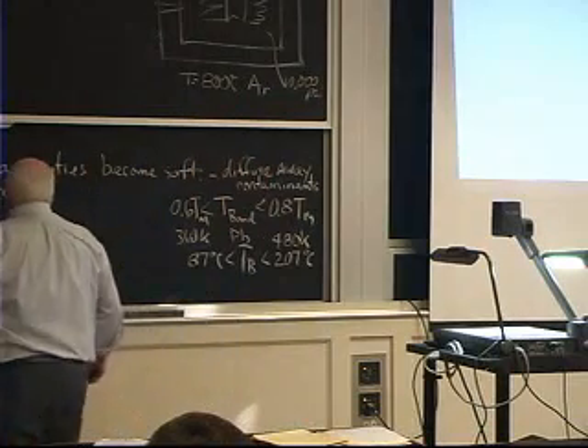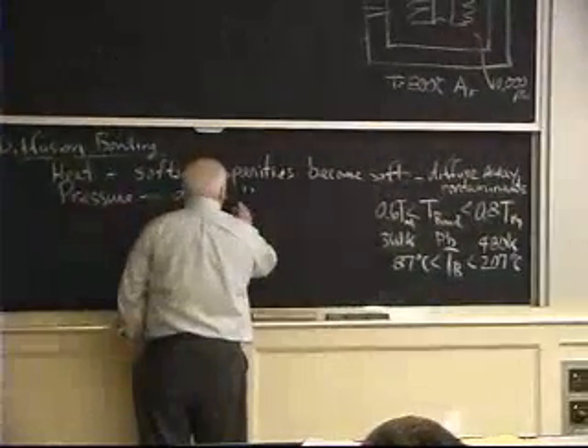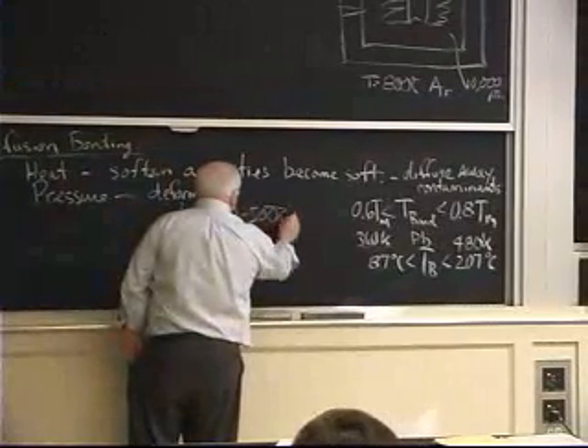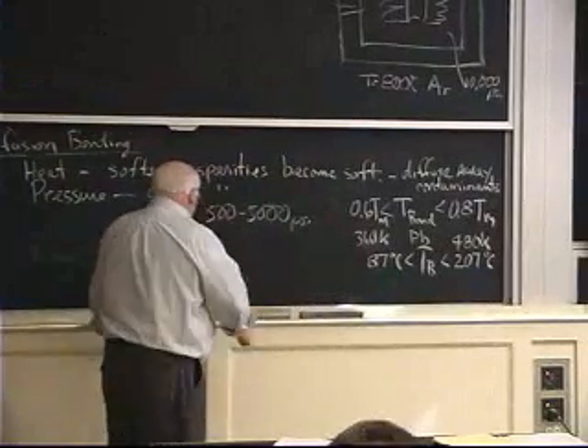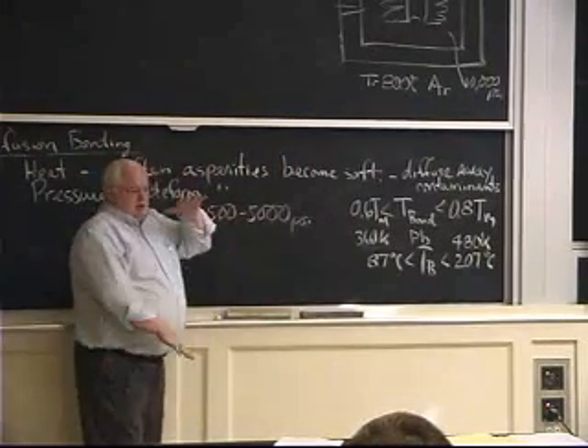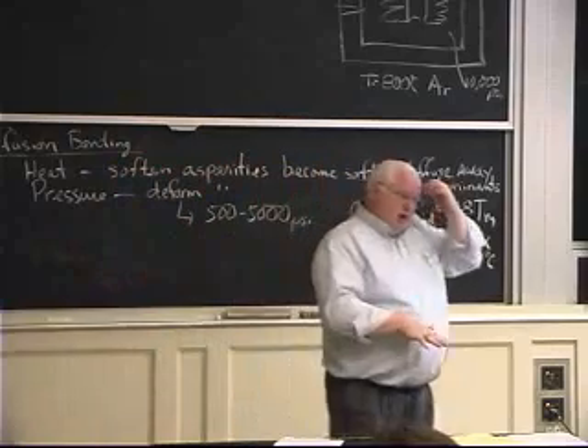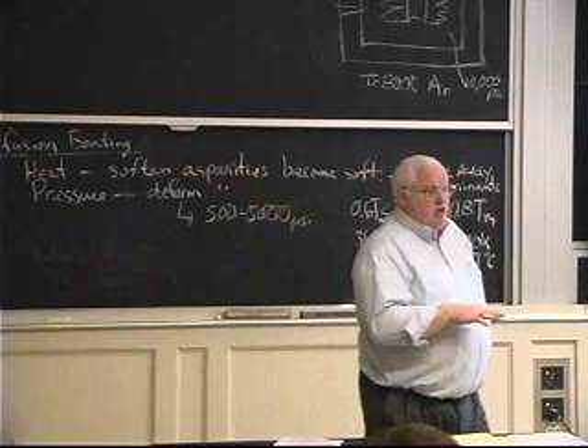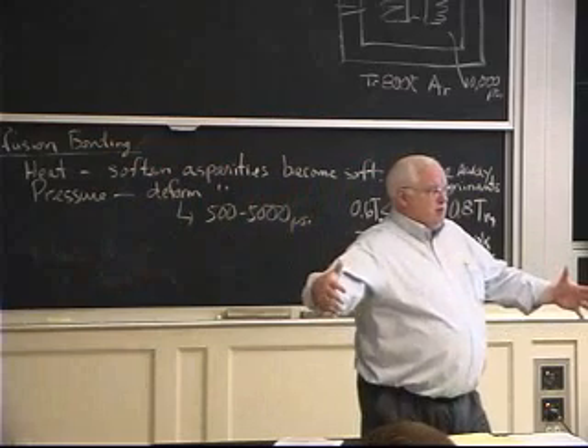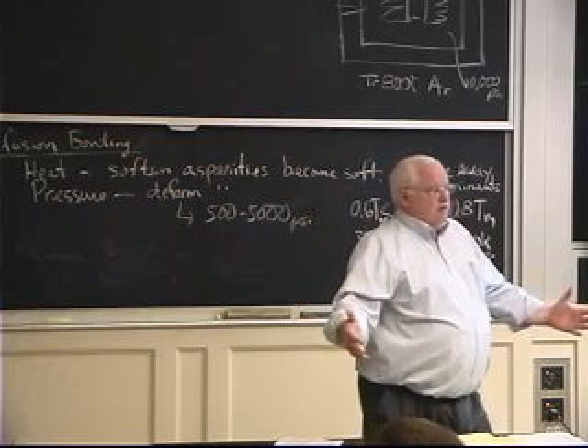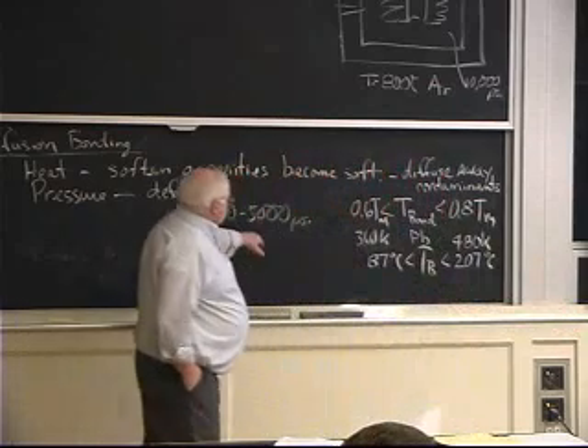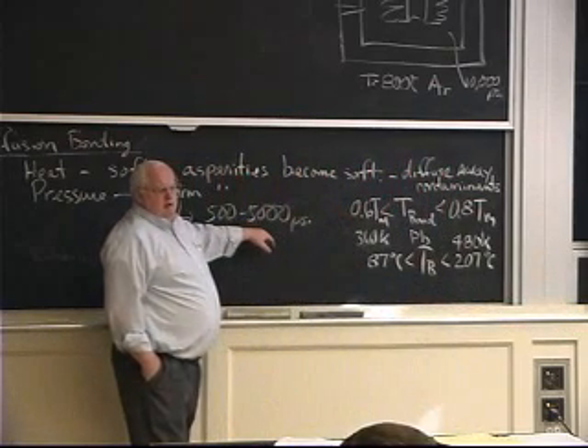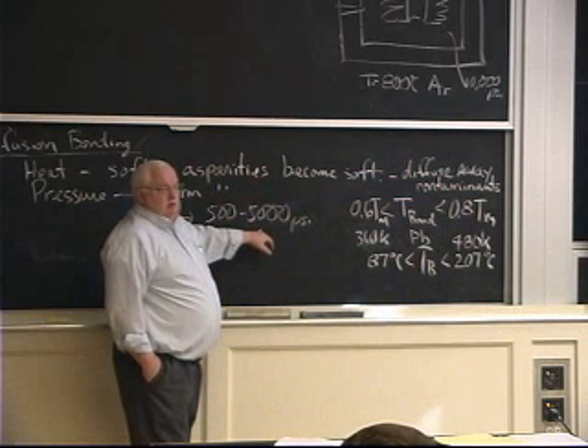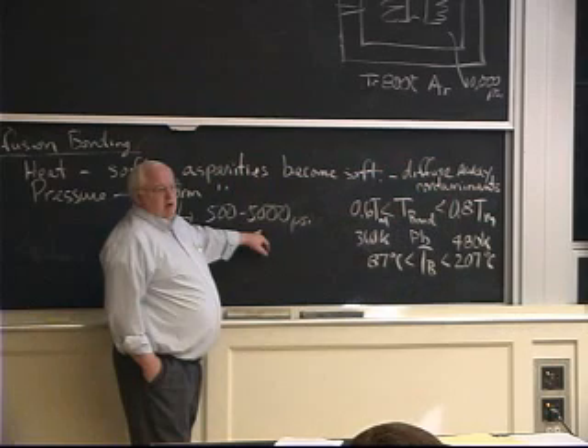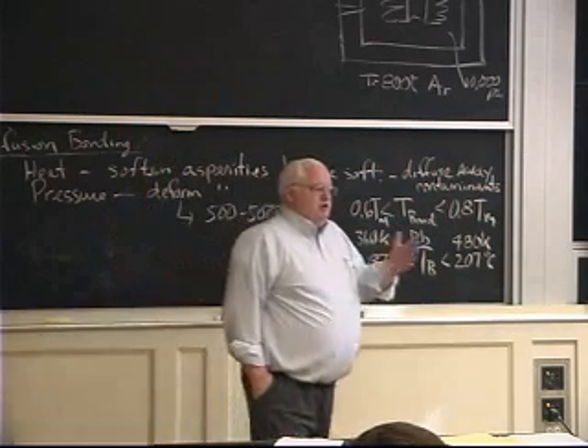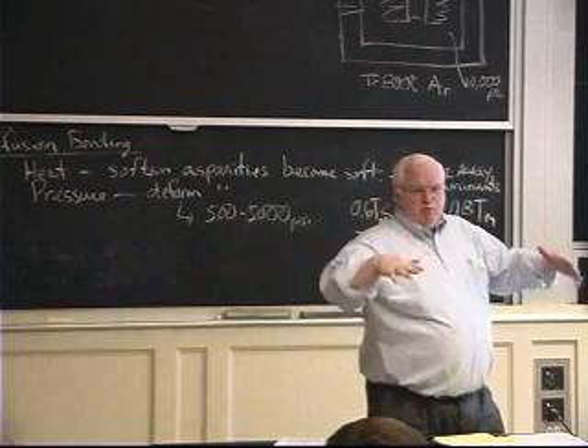Another problem, well, let me talk about pressure. The deformation, so the temperatures are in that range. The deformation pressures are typically in the 500 to 5,000 psi range. I told you for HIPping it went up to 10,000 psi, and that's because you can do it. But if I'm just taking two complex parts and squeezing them together in a great big hydraulic press to get the bond area, and let's say I got 2 turbine discs that are going to diffusion bond together, well, I'm going to have a 5,000 ton press with lots of square inches to be able to get these types of pressures. And in fact, one of your homework problems, I described at the time, probably still is, the world's largest diffusion bonding press. And I don't even remember what the numbers are, you can look at the homework problem. But Mitsubishi Heavy Industries built it to be able to diffusion bond and just make great big steel plates.